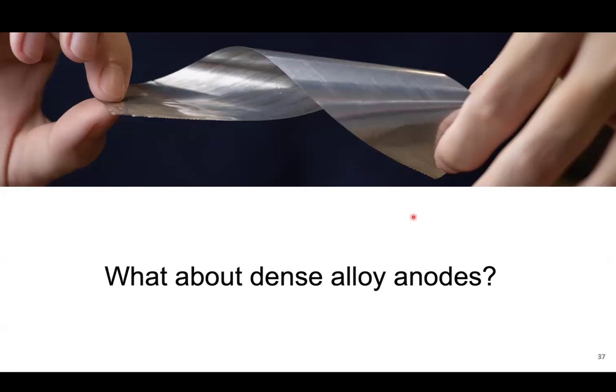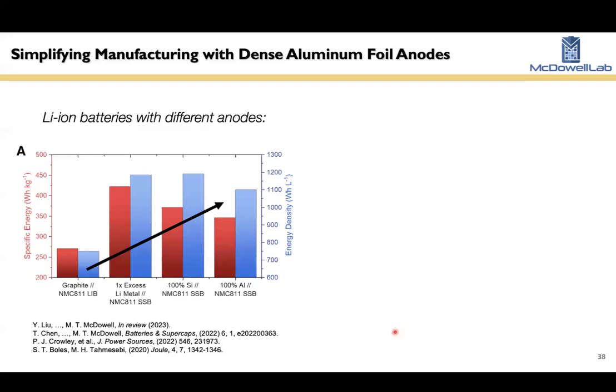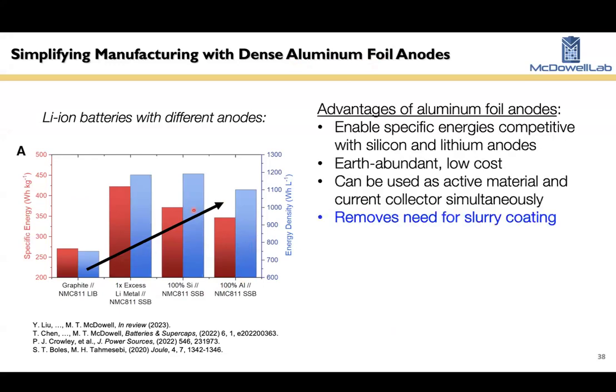This would be highly advantageous because a metal foil that stores lithium is 100% a lithium storage material. There's no other composite structures. They're easy to manufacture. Especially aluminum-based materials are used widely and are low cost. And so we've been focusing on figuring out if we can use dense foil-based alloy anodes in solid-state batteries. And it's particularly those based on aluminum. Again, the energy metrics are appropriate and exciting for aluminum-based materials, similar to silicon-based materials.